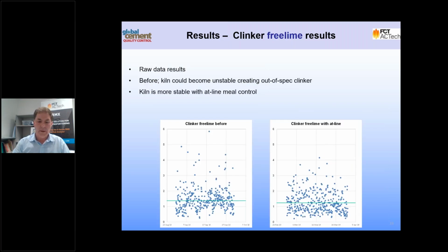So this time I've got the clinker results, but here we're looking at the free lime, and again we've got free lime data for 1 month before the introduction of the online analyzer, and the free lime data for another month after the analyzer. There's quite a broad spread in this data, particularly the one on the left, which was beforehand, and it's these high points that are of interest because they represent very unstable kiln operation. And what we can see is that even with increased C3S, which previously did cause stability problems, we're not seeing that same spread of high values.